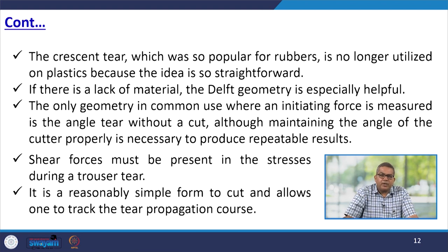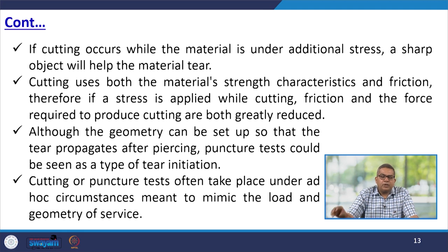If there is a lack of material, the delft geometry is especially helpful. The only geometry in common use where an initiating force is measured is the angle tear without a cut, although maintaining the angle of the cutter properly is necessary to produce repeatable results. Now, shear force must be present in stresses during the trouser tear. It is a reasonably simple form to cut and allows one to track the tear propagation course. Now, if cutting occurs while the material is under additional stress, a sharp object will help the material tear.